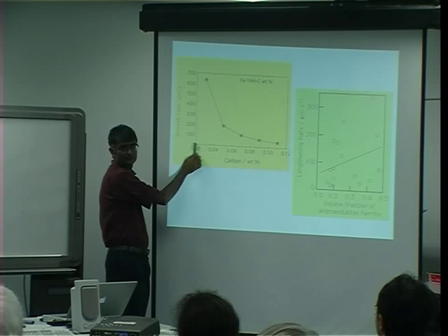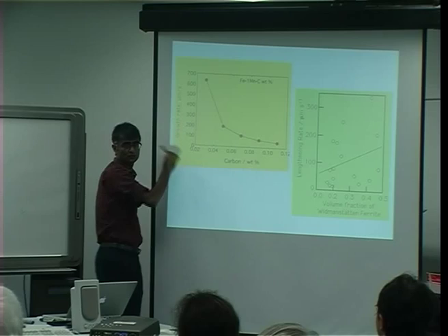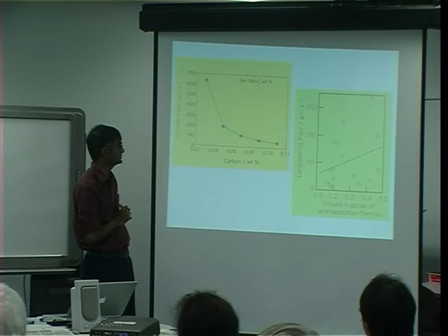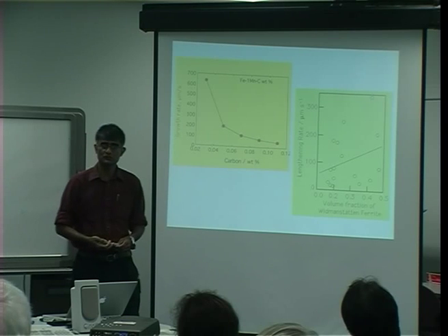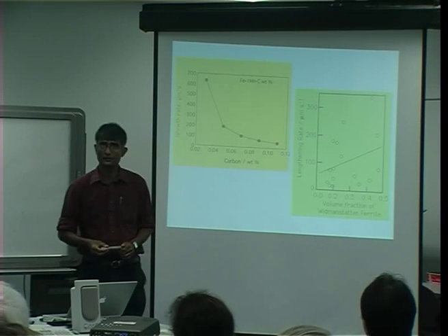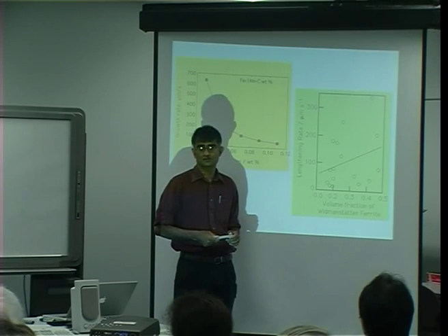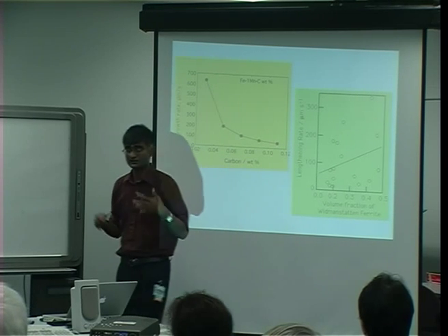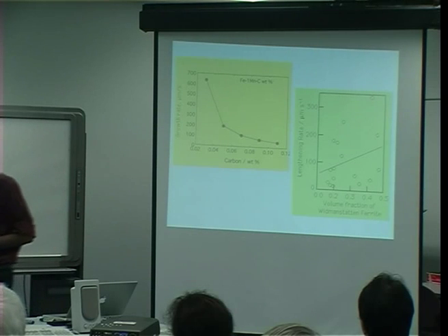Again, notice that the growth kinetics are sensitive to carbon concentration at low carbon concentration, justifying those two different carbon equivalent equations. So let's see how the volume fraction of Widmanstätten ferrite varies with the calculated growth rate. You can see that that's fairly random. There's no correlation between the volume fraction of Widmanstätten ferrite and the calculated growth rate. And there's nothing wrong with the growth rate calculations.